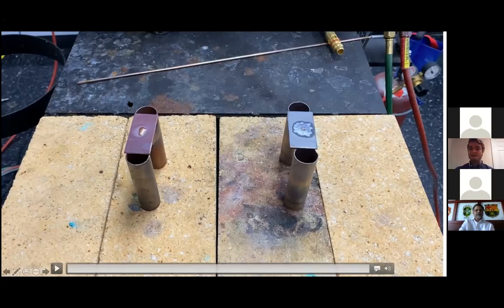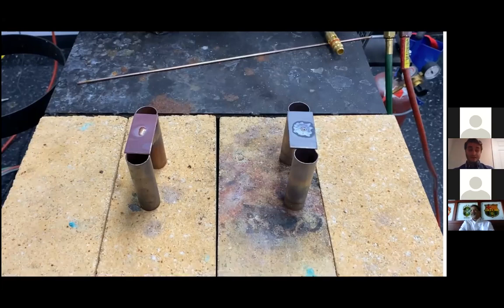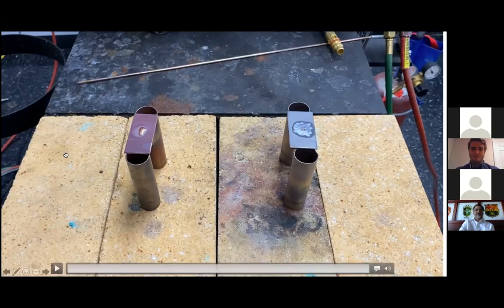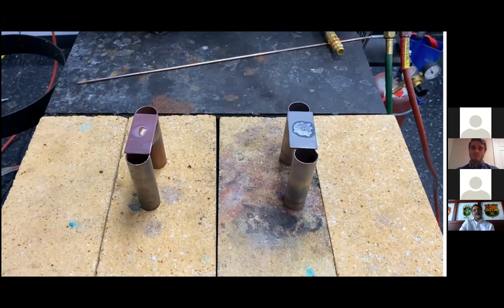And the reason behind that, if you look into the combustion rate on air fuel, on a flame for acetylene and propane: when we are talking about acetylene, it is 1.5 oxygen molecules to 1 of acetylene, and when we're talking about propane, it is one propane molecule to 4, up to 5 molecules of oxygen. So when we are having an air fuel where you don't have the source of oxygen, you don't have as much oxygen as you have on an oxyfuel torch, so the tip is missing some of these oxygen molecules. So maybe in the air fuel torch, it's bringing only 2 or 3 molecules of oxygen to the torch.